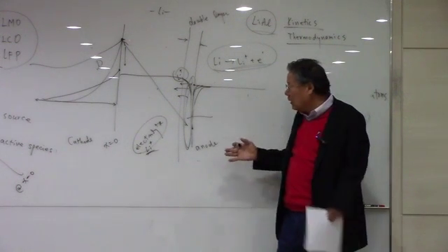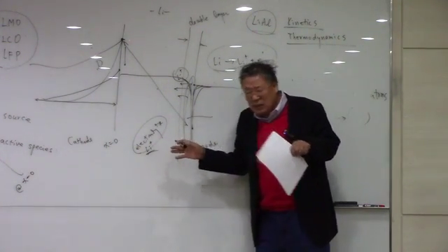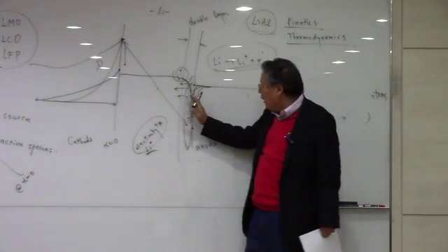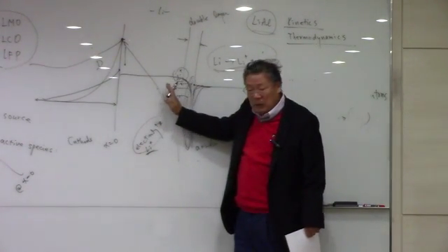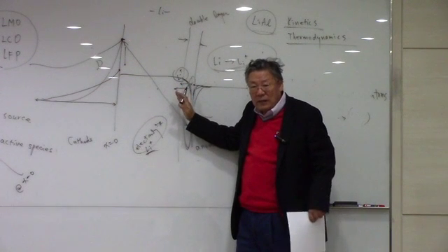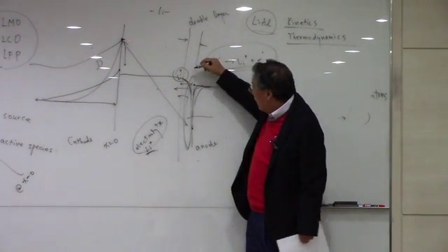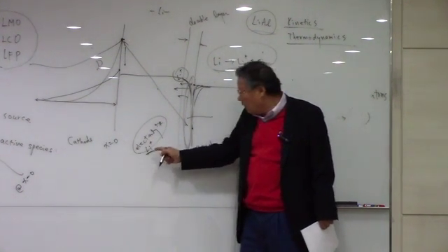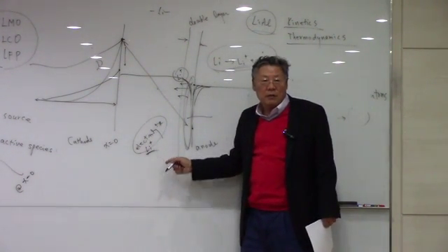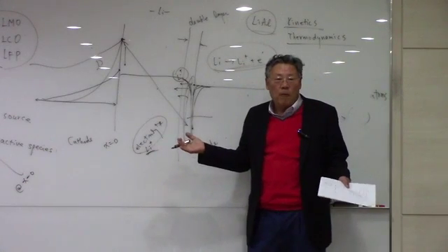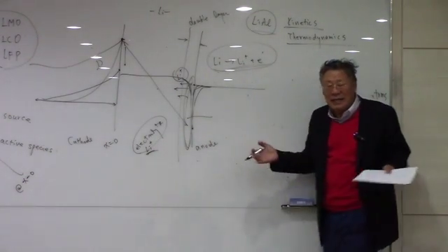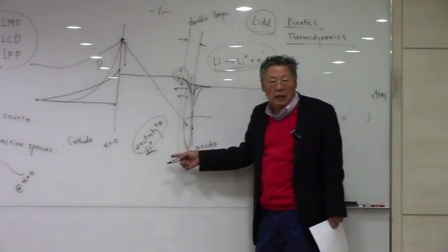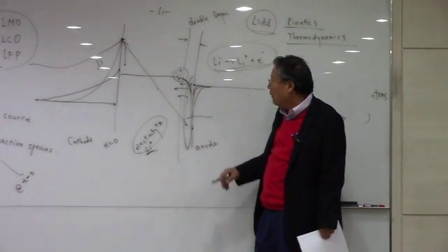Okay, if this situation continues for a long time, then this layer is going to be widened in distance. At the same time, some dissociation of the electrolyte will happen. Gas is going to be formed, bubbles are going to be formed, and any other second phase is going to be formed in the electrolyte. Okay, the electrolyte is not going to be stable.